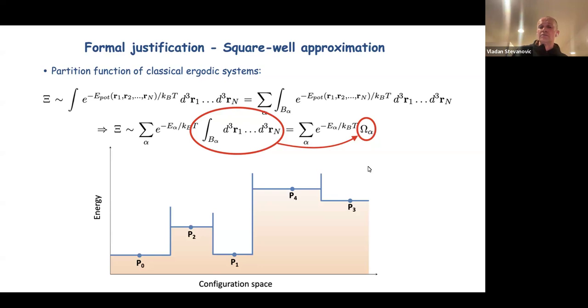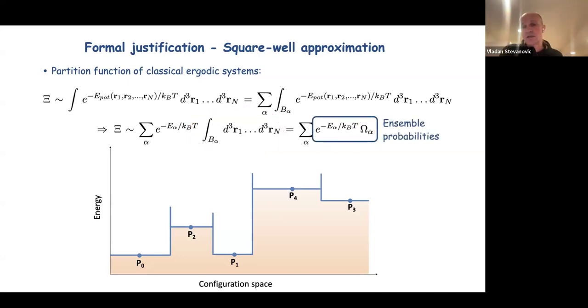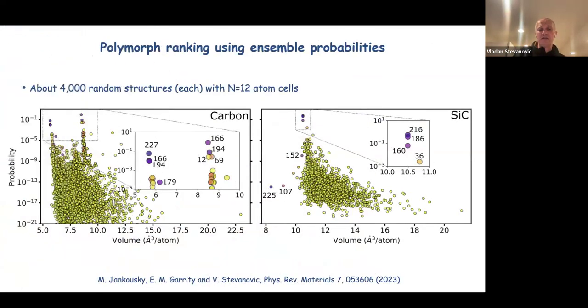And those degeneracies pretty much appear in what we would normally refer to as the ensemble probabilities in statistical mechanics. So the ranking that I showed you on a previous slide was pretty much done exclusively on these omegas. One can then ask, what if you bring the energy into the picture, and how would the ranking look if you now rank systems based on full statistical mechanics ensemble probabilities? And we did that on elemental carbon and silicon carbide.